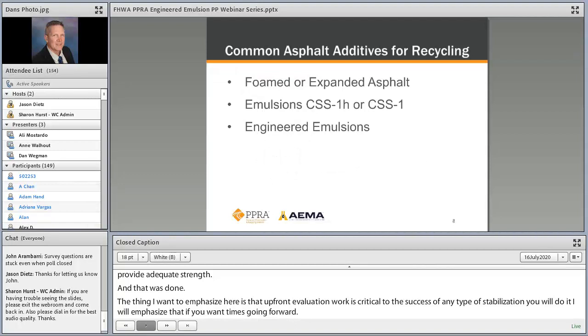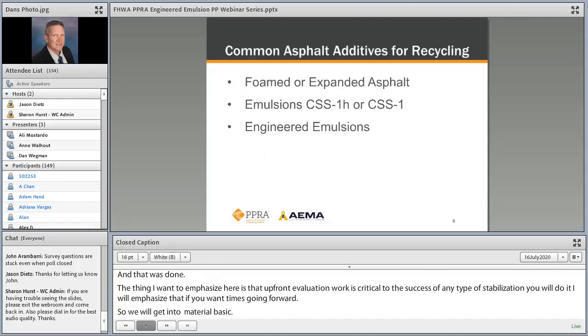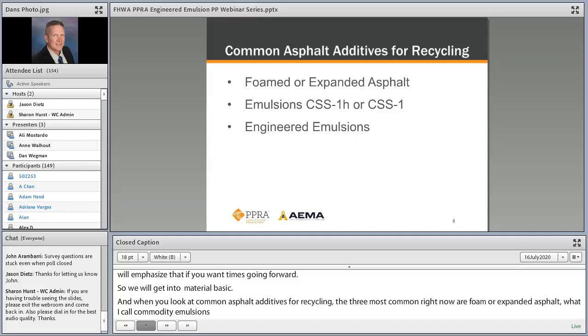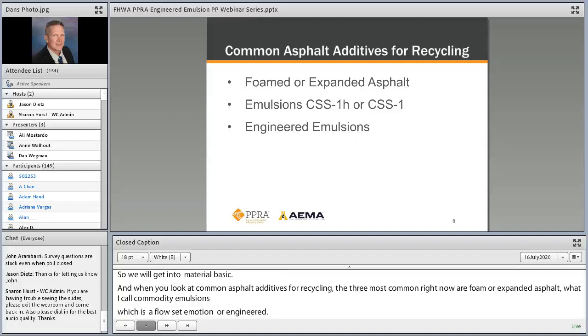And when you look at common asphalt additives for recycling, the three most common right now are foamed or expanded asphalt, what I call commodity emulsions, which is basically a cationic slow-set emulsion, or engineered emulsions. And really, for those of you that are not familiar, a foamed or expanded asphalt is basically bringing hot AC out to the job, and it needs to be really hot. I mean, you're usually talking about over 300 degrees for that foaming process to function properly.